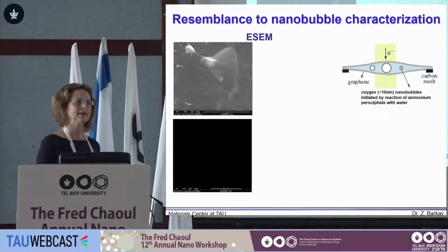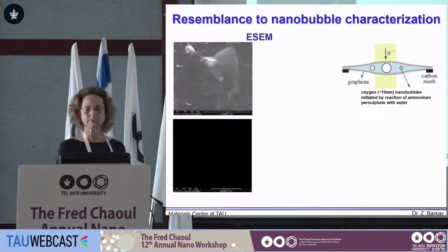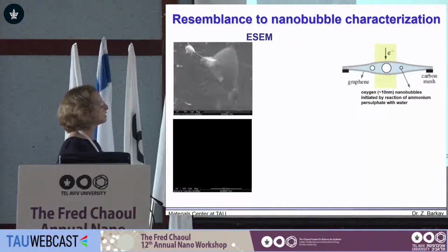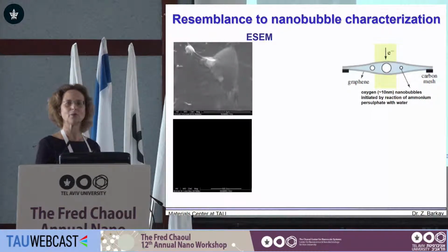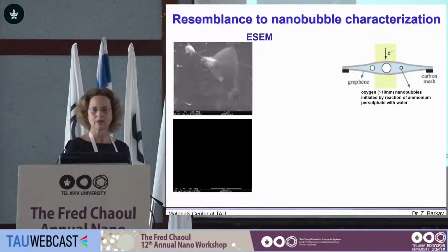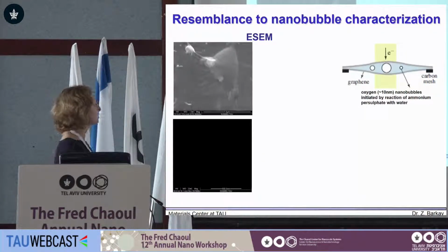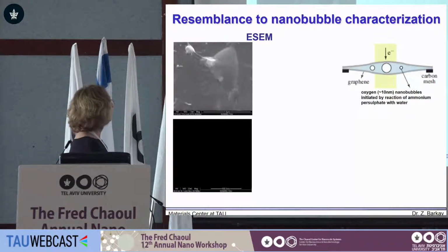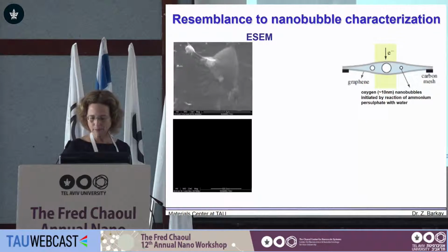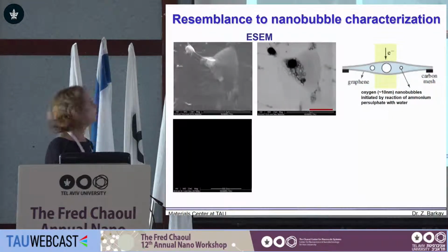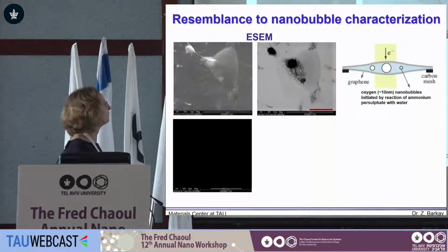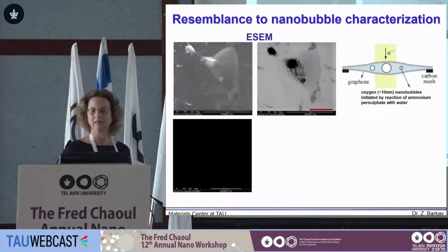Another group was working at the same time on nanobubble characterization. They provided me a sample, a graphene sample in which there was oxygen bubble encapsulated - not the regular hydrogen bubbles we're familiar with from radiolysis, but oxygen bubbles initiated by ammonium persulfate interaction in water. Here you see the SEM image - this is the surface, you see a pocket. When we look at the transmission information, what we actually see are bubbles of 10 nanometers, and they are quite stable at the time of imaging.